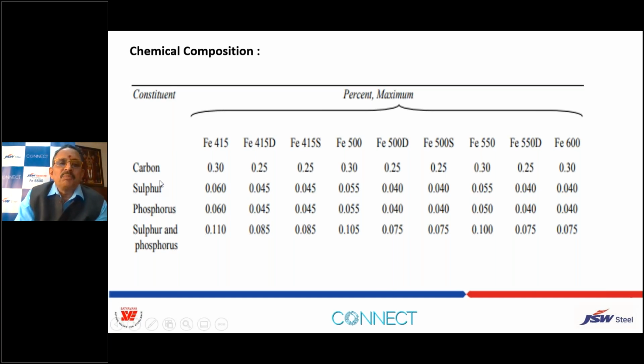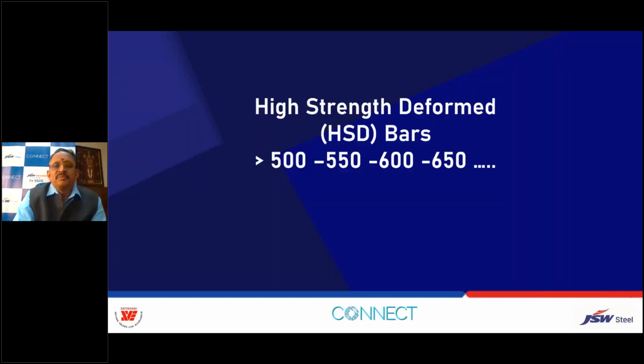So this is the chemical composition. We are all aware, if it is just 550, it is 0.3 carbon content. And if it is 550D, carbon content is reduced to improve the ductility. And then the sulfur and phosphorus also are reduced to increase the fire resistance and also the overall ductility. So these are all the guidance as per the IS provisions.